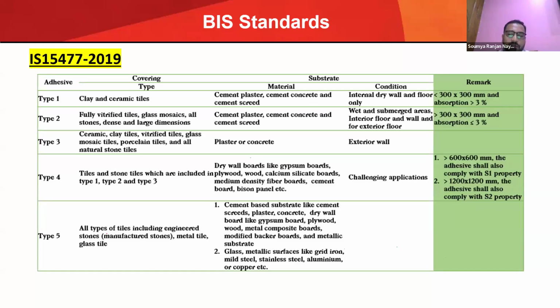Type 1, type 2, type 3 are cementitious tile adhesives. They are made with cement and polymers. Type 5 are polyurethane and epoxy-based tile adhesives. They use polyurethane and epoxy to bind tile with different substrates like gypsum board, plywood, wood, metal, steel, and copper. Any metal you name, they have the capability to hold the tiles and stones to the surface.